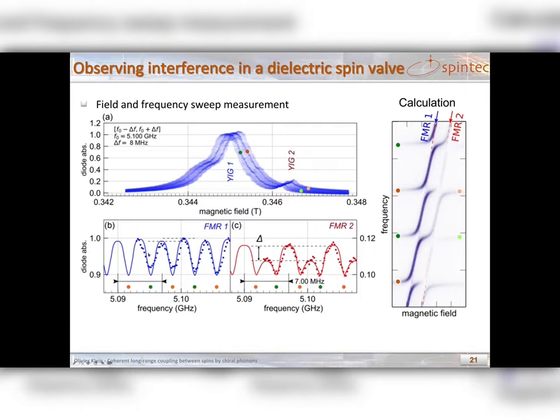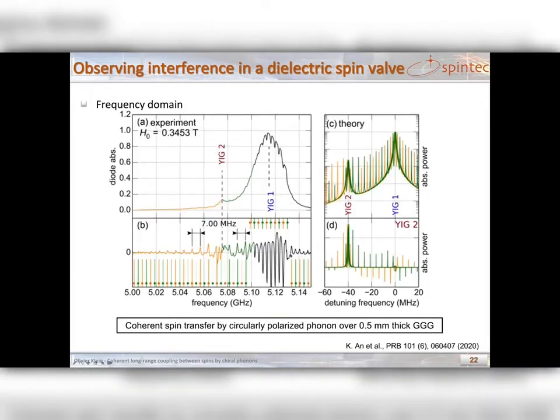This can be shown also experimentally by following the intensity at the maximum of the Kittel mode 1 or at the maximum of the Kittel mode 2, and what you can see is this double modulation. And you can see this contrast appearing between odd and even phonons that is typical of an interference effect. So you can see this interference also in the frequency domain.